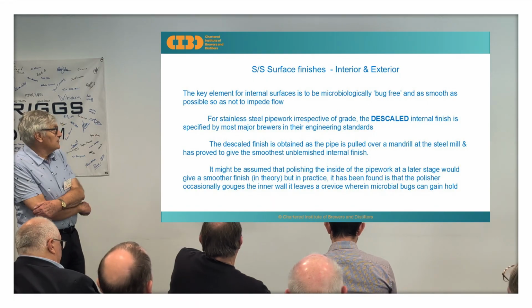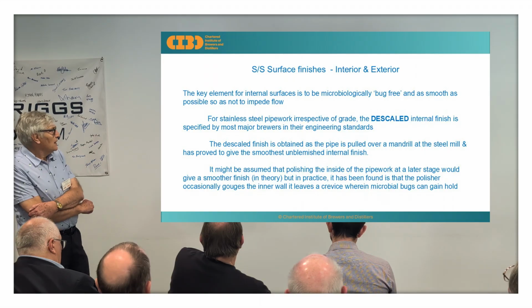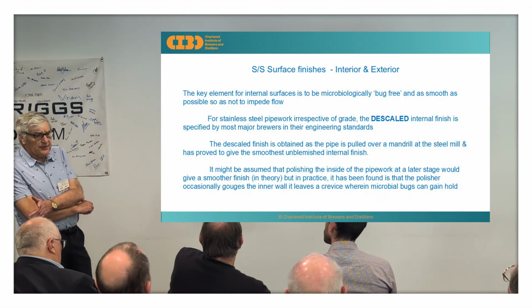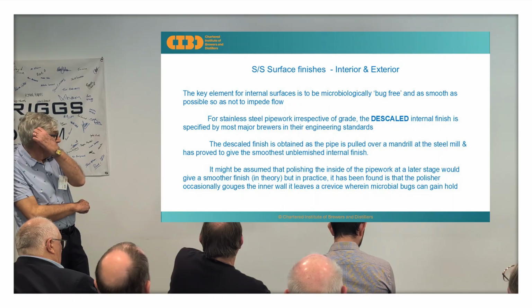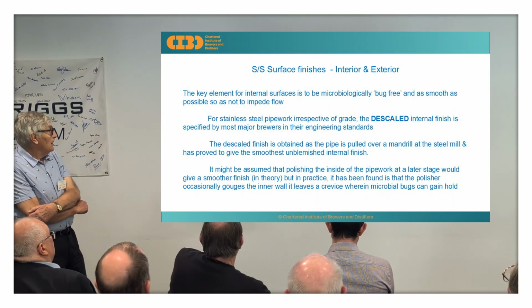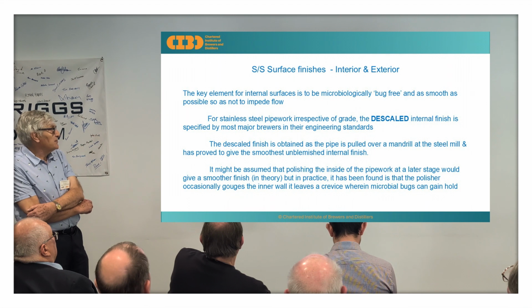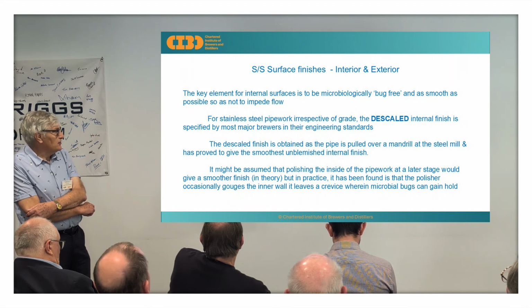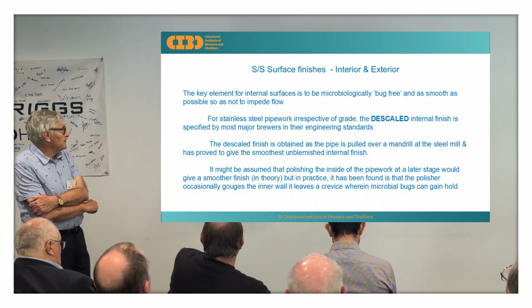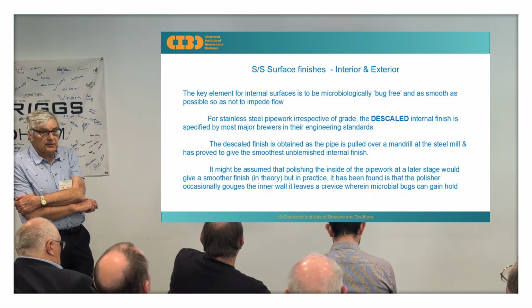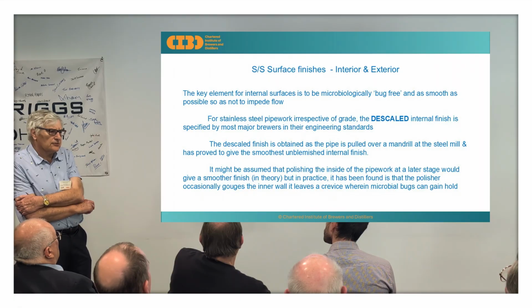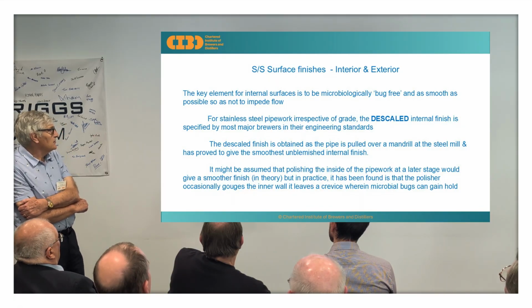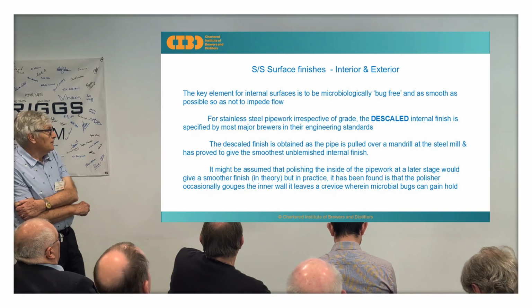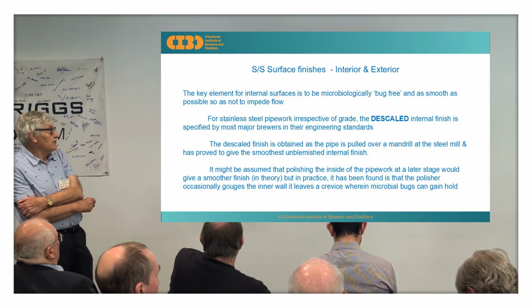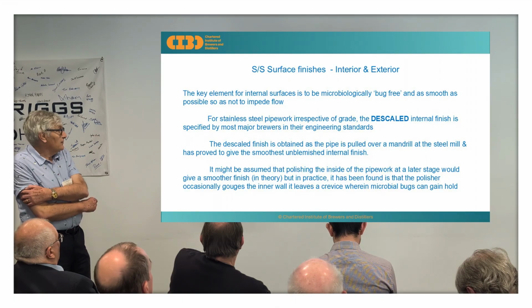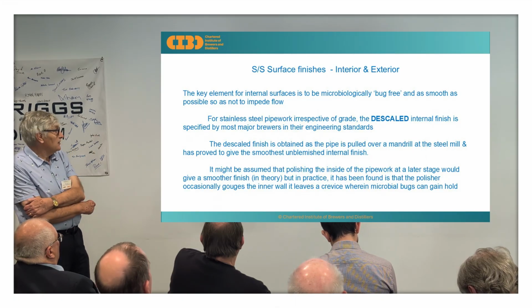Stainless steel surfaces and finishes. One of the things that brewers go for is a microbiologically bug-free finish. For stainless steels, irrespective of grade, the descaled internal finish is specified by most major brewers in their engineering standards. I know that Molson Coors and Bass use those. The descaled finish is obtained as the pipe is drawn over a mandrel at the steel mill, and has proved to give the smoothest and most uniform internal finish.